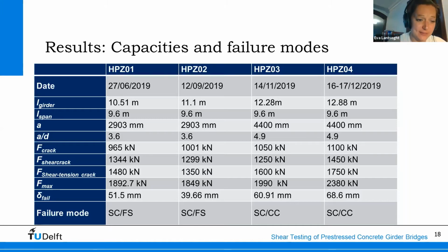Here you can find the values of the externally applied load for which we had the first flexural crack with F cracking, the first shear crack with F sub shear crack, the first shear tension crack in the web with F shear tension crack, and then the maximum load with F maximum, and also the associated deflection.